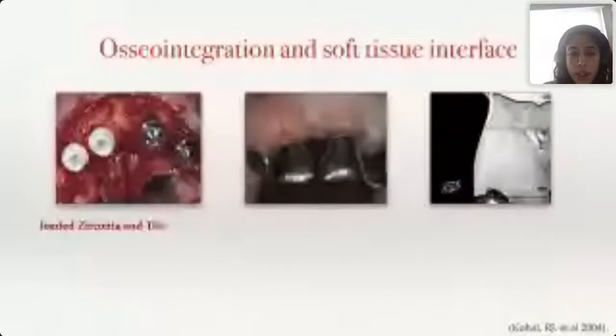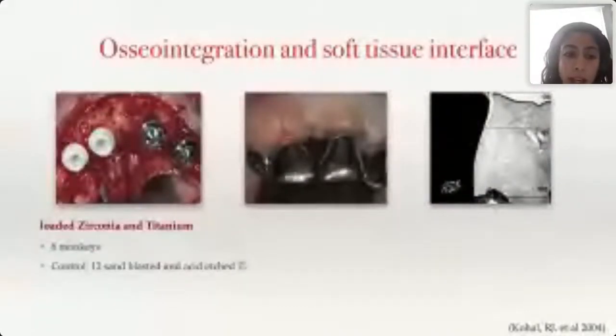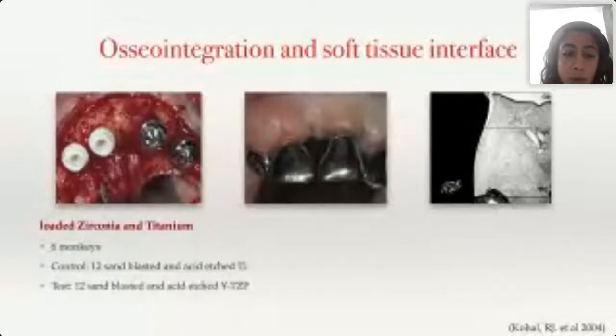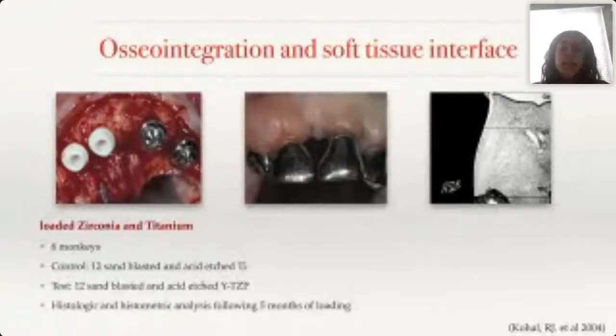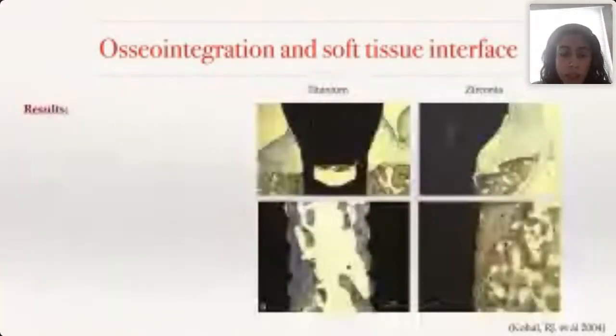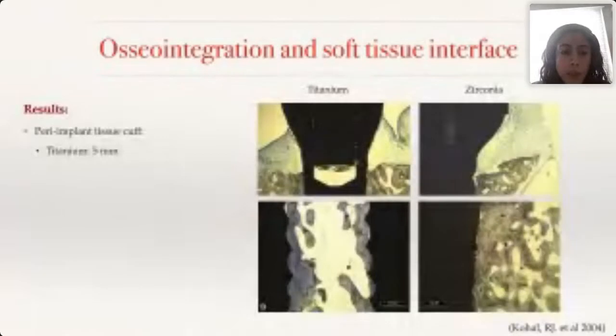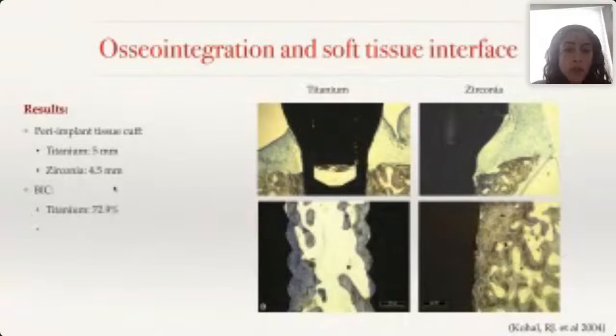The next study was done in 8 monkeys, with 12 sand blasted and acid etched titanium, and 12 sand blasted and acid etched Y-TZP zirconia implants. Here they also evaluated the soft tissue cuff, the area of the connective tissue, and the junctional epithelium. The peri-implant tissue cuff was very similar between titanium and zirconia, 4.5 to 5 millimeters, and the bone to implant contact was 72 versus 67, with no significant difference between groups.